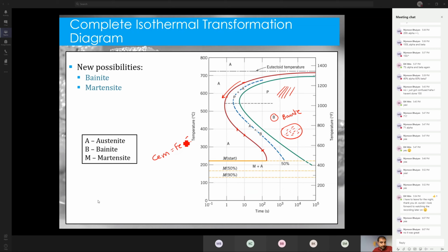They called it bainite. And the last interesting thing to see here is, well, what happens below this temperature here? So suppose I manage to cool my material from high temperature to low temperature so fast that not even a second lapsed before the temperature came down to 200 degrees or to room temperature. So that's what would happen if you took something red hot right out of the furnace and dipped it in water. It cools down within a fraction of a second. So there is no time for diffusion. There is no time to make pearlite, the lamella. There is no time to make bainite, the needles. There is no time for any of that. In that case,